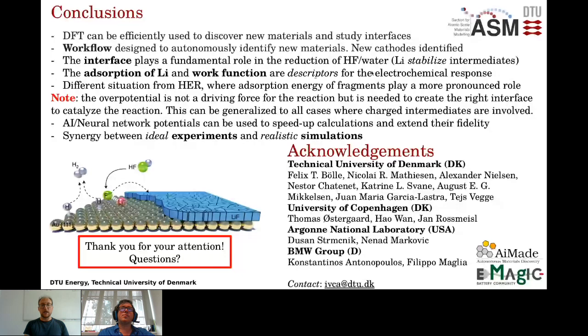This can actually have very large implications also in catalysis in general, because for the first time, the overpotentials that are usually used for running the reactions are, in this case, used to create the right interface. The right interface means having lithium pre-adsorbed on the interface that will be a catalyzer for the reaction, whereas usually an overpotential is used as an activation energy.